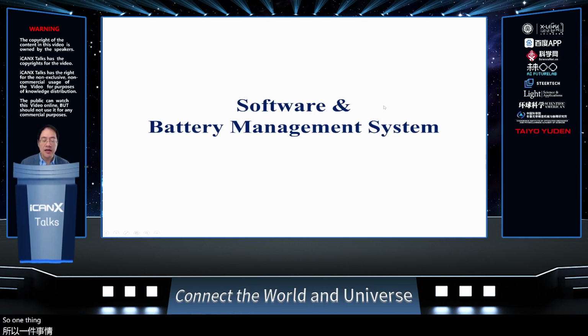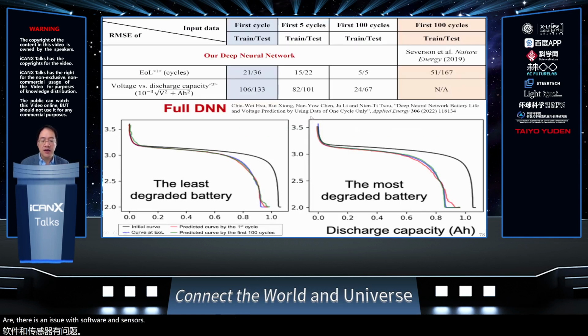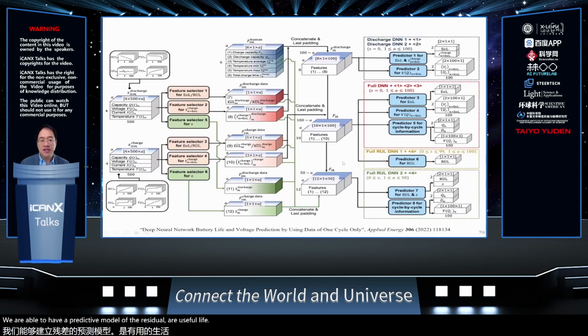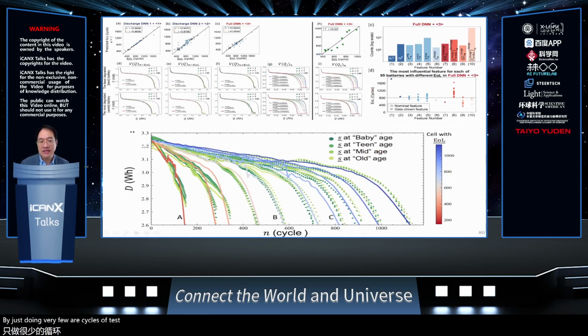So one thing is, going beyond the battery chemistry, there is the issue of software and sensors. In a recent work, we've shown that by using a neural network to study the discharge data of battery cells, we're able to have a predictive model of the residual useful life by doing very few cycles of testing. So what you see here is that you have some used batteries, and some of them only have residual life of less than 200 cycles. Some can still have more than 1,000 cycles of residual life.